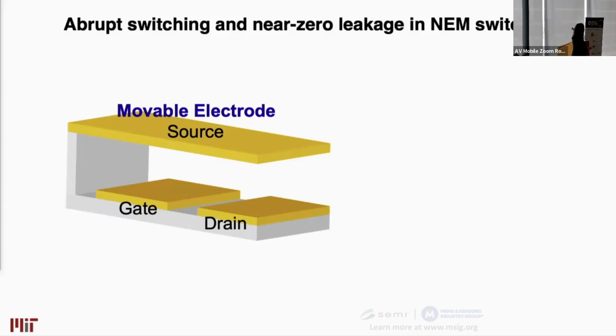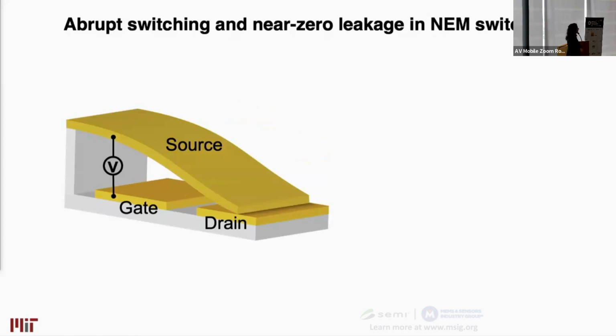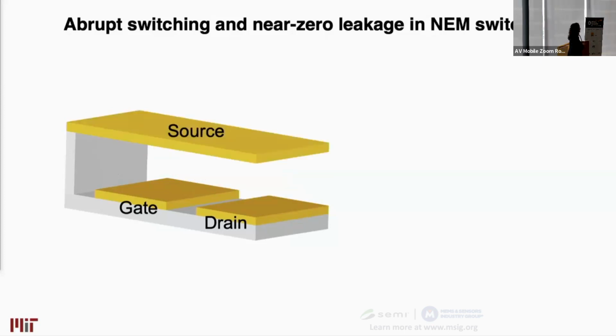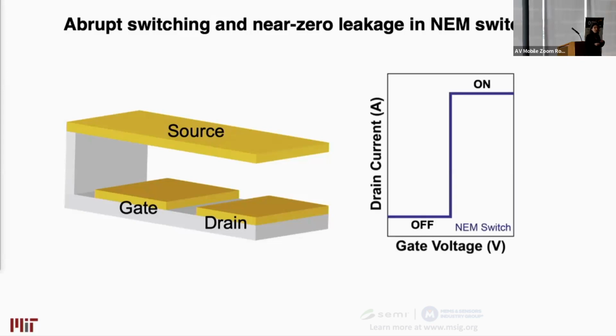So as you're probably aware, electromechanical switches in the simplest form would look like a relay that I'm showing you here on the screen, where you have movable electrodes, you apply a voltage, electrostatically actuate your device. As the contacts come into contact, your device turns on. If your elastic restoring force is sufficiently large to overcome surface adhesive forces, you turn off your device. And this mechanical process allows electromechanical switches to have an abrupt switching performance with near zero off-state leakage and a very large on-to-off current ratio. So that allows them to become a suitable platform for energy efficient applications, complementing conventional transistors.